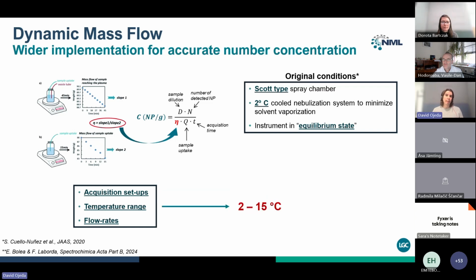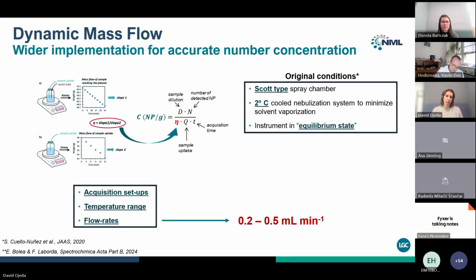To test the temperature range, we went from the original condition of 2 degrees and wanted to see the effect of solvent vaporization by increasing the temperature up to 15 degrees. And finally, for the flow rates, we studied a range that most single particle ICP-MS studies normally use, from 0.2 to 0.5 milliliters per minute.